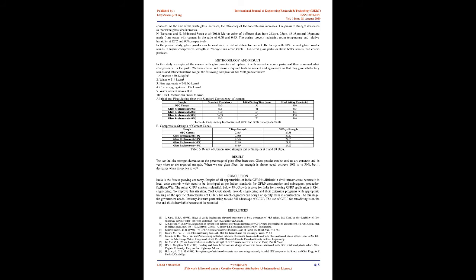Literature review. M. Iqbal Malik and Muzaffar Bashir et al., 2013, studied concrete samples tested for compressive strength, split tensile strength, durability, water absorption, and density at 28 days of age, and the results obtained were compared with normal concrete. Replacing 20% of the aggregates with waste glass increased the compressive strength by 15% in 7 days and by 25% in 28 days.